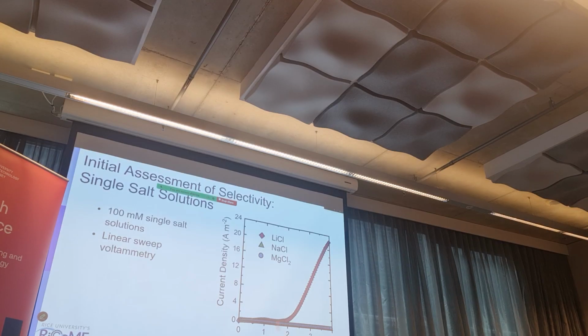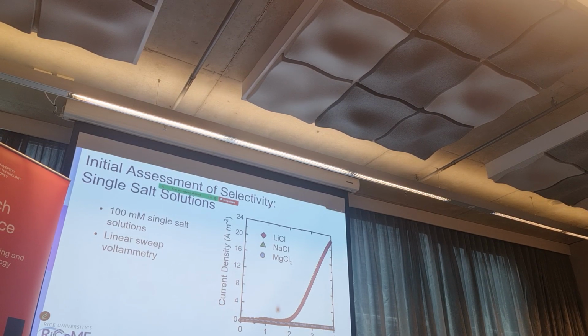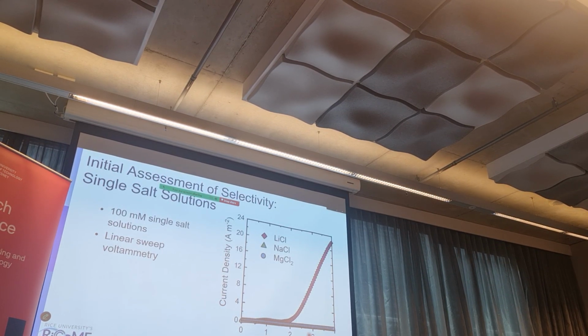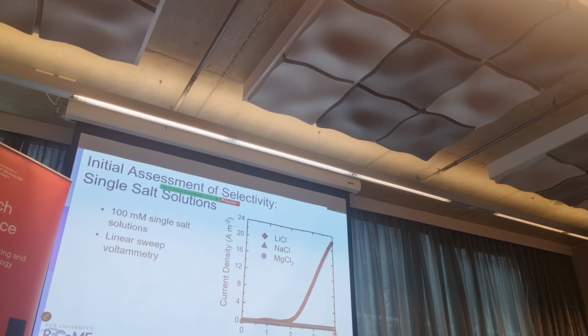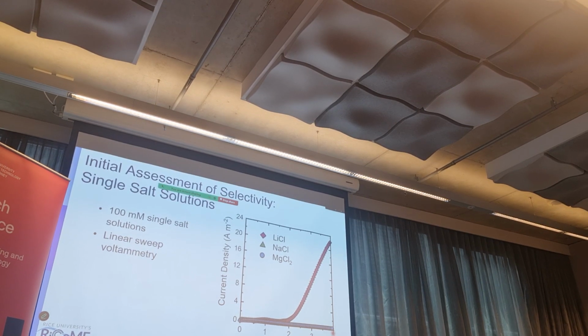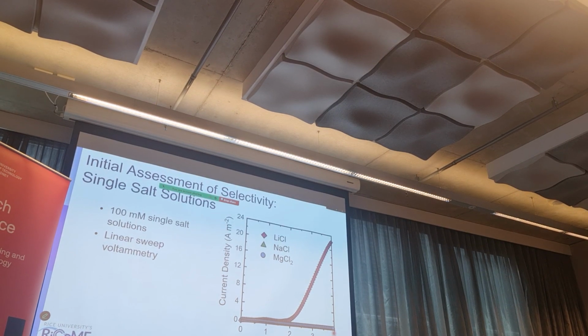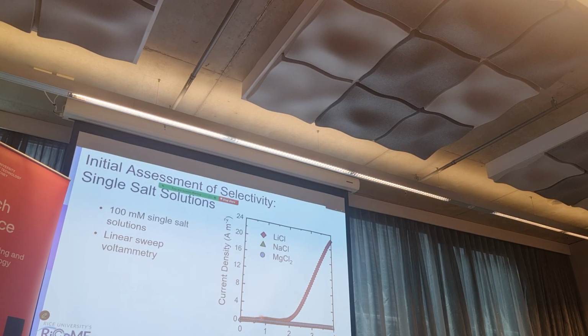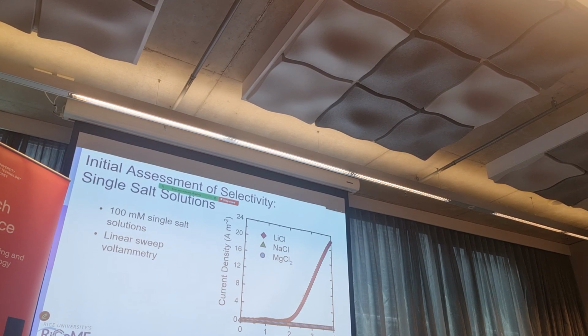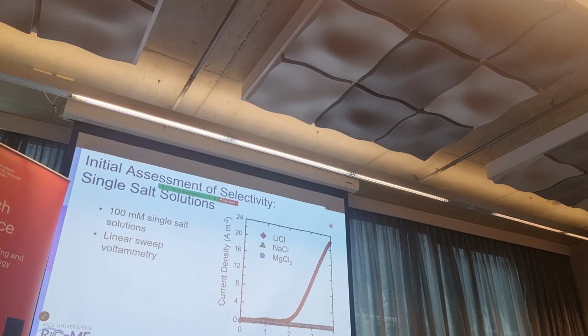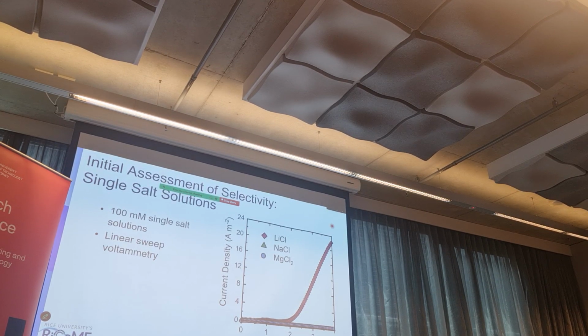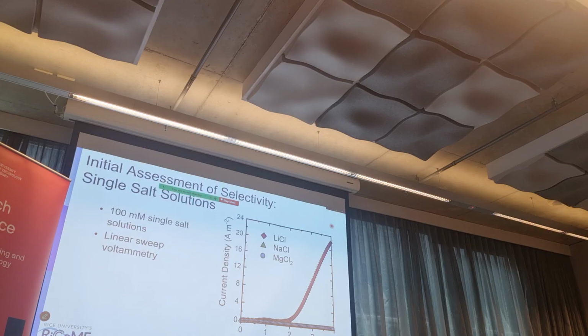With sodium chloride and magnesium chloride, we changed the voltage, increased and decreased it, and nothing came out - this solid state electrolyte in the electrodialysis process could not pass sodium or magnesium. However, with lithium chloride, above a certain voltage we start to get current, and as we increase the voltage, the current increases a lot, so a lot of lithium comes through, probably by electromigration. I'll talk more about the mechanism.